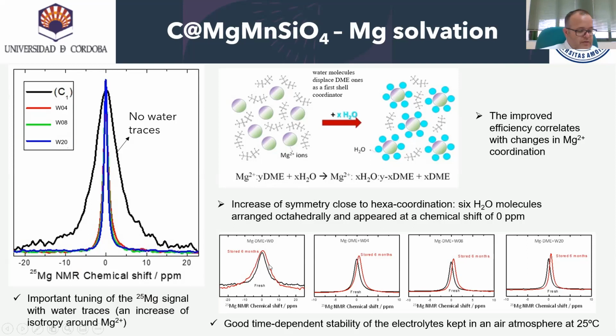A satisfactory time-dependent stability of the electrolyte is found also when they have been kept under air atmosphere during 6 months. The line width was preserved, as we can see. However, the water-free electrolyte suffered an increase of the line width higher than 15 ppm, which correlates with the null electrochemical activity.